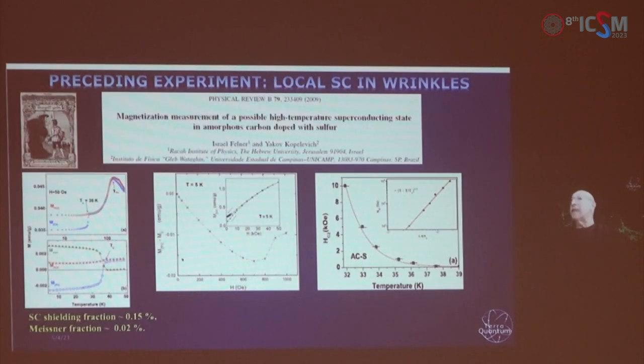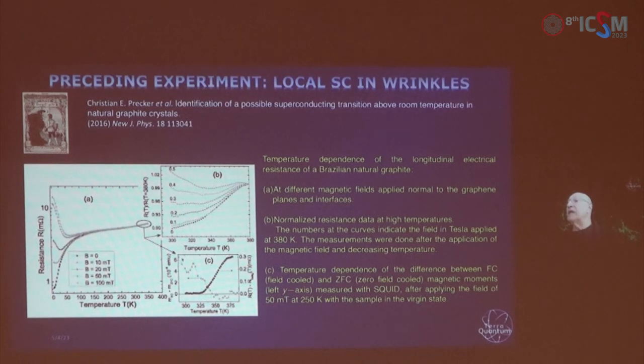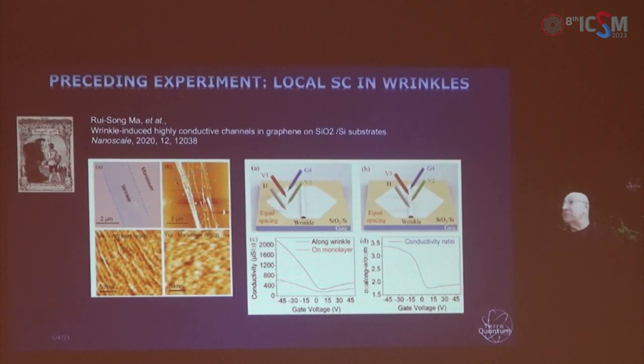And this is the experiment which actually shows that this local superconductivity is related to the wrinkles, and these data were confirmed by further measurements. Okay, so this is again enlarged data showing the transition from superconductivity in the wrinkles to the insulating behavior as we increase the magnetic field. And then there were local measurements which finally identified that this local superconductivity is indeed due to the wrinkles.